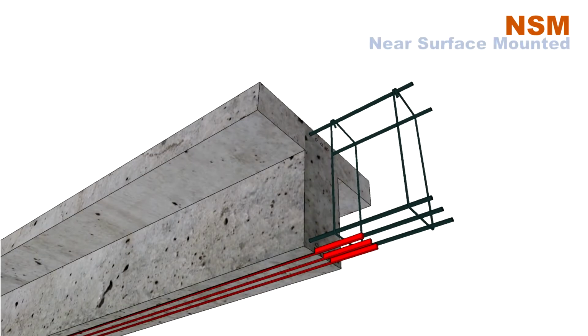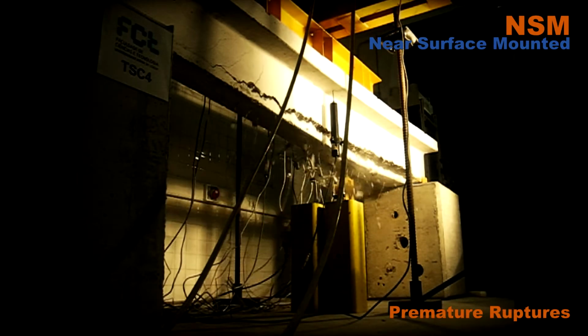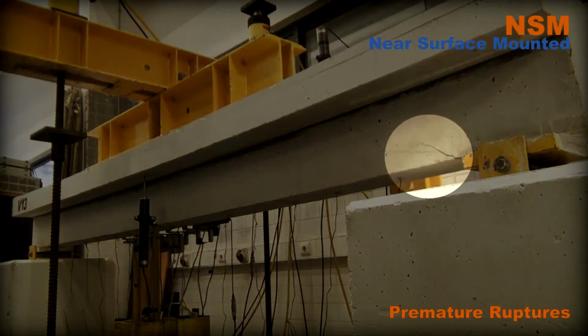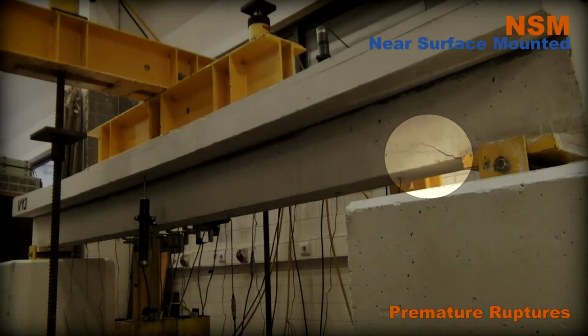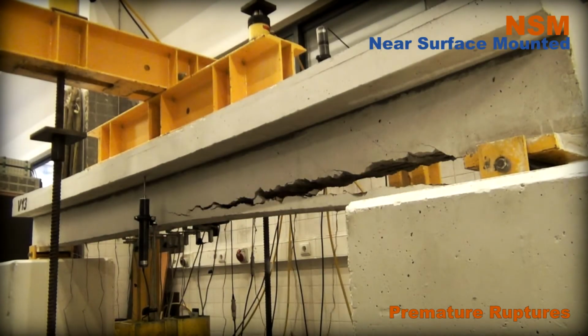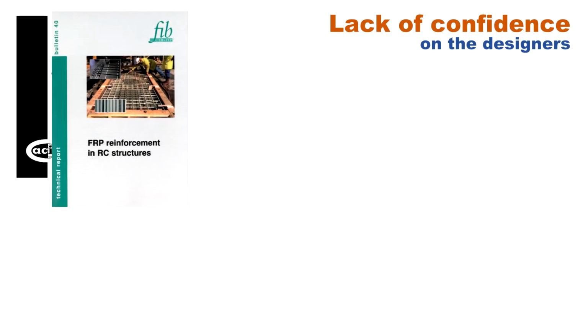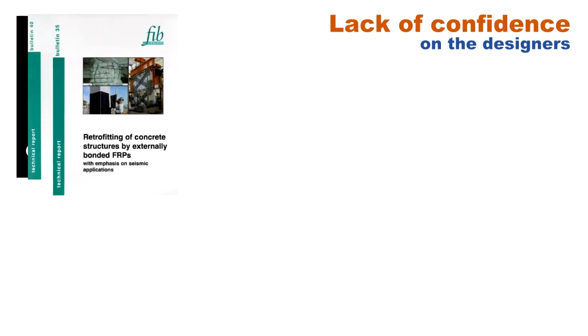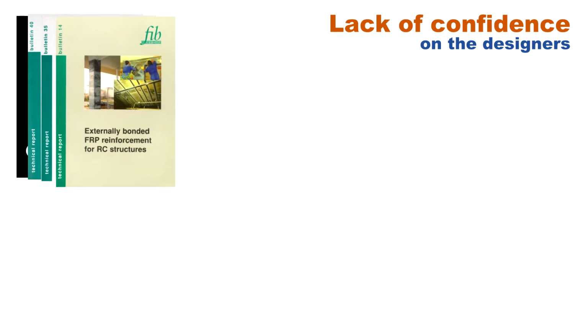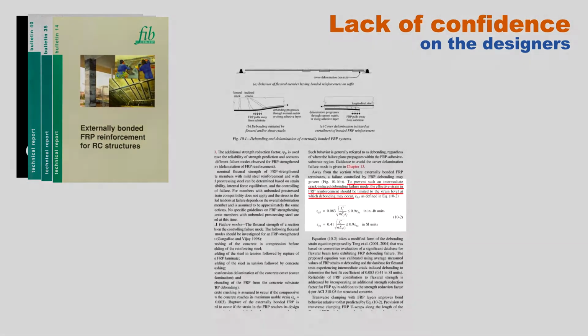On the other hand, the NSM technique presents a rupture by splitting of the concrete cover in the bottom of the beam. Both EBR and NSM types of strengthening provoke brittle failures due to the splitting of the concrete cover. This inefficiency of the system generates lack of confidence on the designers. So, they tend to produce a more conservative design of the structural strengthening, which leads to lack of optimization of